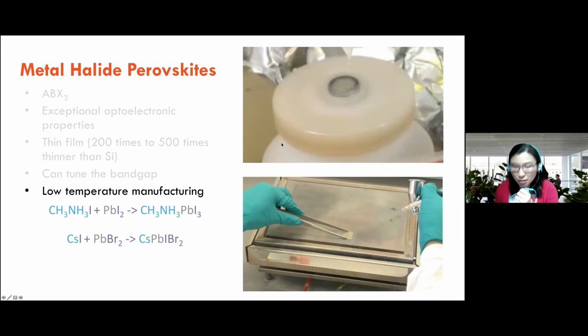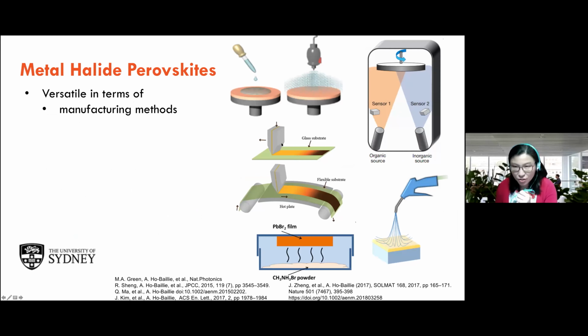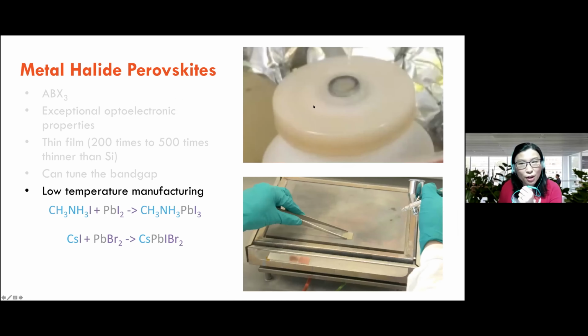see if I can, oh, okay, I can't. So I was supposed to show you a video of how the student can make the perovskite film very quickly using drop and spin coat process, or even the spray process. So this spray gun is used for artists. So we just buy it from the artist shop, and we managed to make a cesium lead iodide bromide cell.